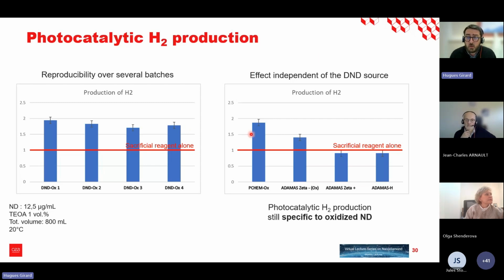And also we tried with different sources of nanodiamond. So here, for instance, you can see that for all the study, we use particles from Plasma Chem that we oxidize by ourselves with our own method, but we compared this with particles from Adamas. So we use the oxidized particles as received, but even as received, without any further oxidation, you have this overproduction. While if we used the positive zeta particles from Adamas, or particles from Adamas that we hydrogenate by ourselves, you can see here that we have no more production of hydrogen.